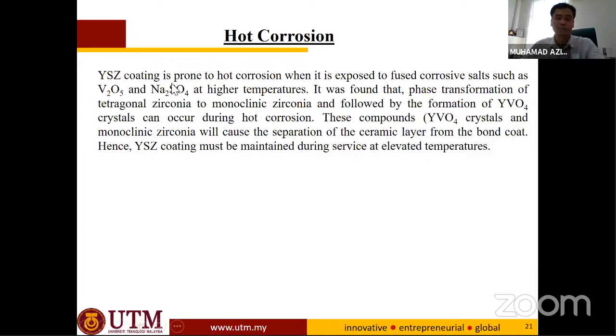So this ceramic, what is the good thing? They will react with this vanadium salt here. So they will create yttria vanadate, YVO4, we call it, a yttria vanadium oxide, which is basically detrimental. So we need to prevent this from happening.